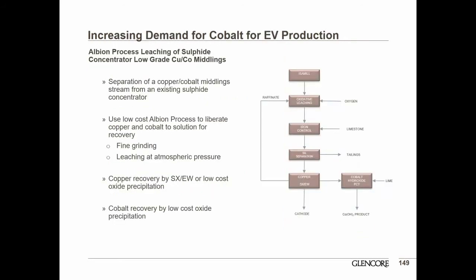The next aspect of improved cobalt recovery that I'll discuss is the Albion process. I won't go into this in much detail. Paul spoke to that earlier. But one of the things that we do see is people throw a lot of cobalt away in the form of low-grade copper-cobalt middlings in many flow sheets around the world. Probably 5 or 6 years ago, these materials weren't economic to treat, but with the cobalt price as it is these days, and with the prices that we see going forward, it's very viable now to start to treat these middlings. The Albion process is an ideal circuit because of the low capital cost and the very simple process.